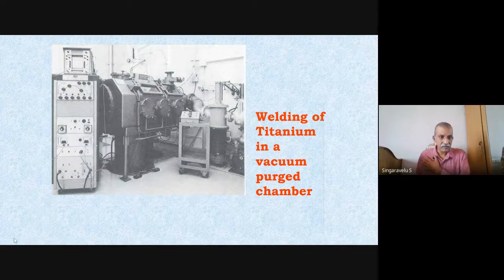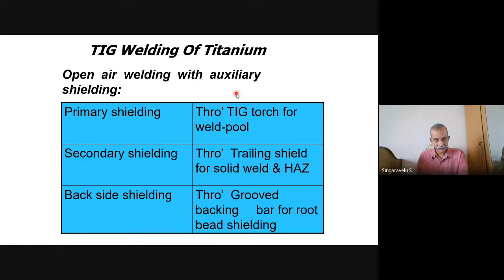Okay. And coming to our shielding, I said, in case of open air, primary shielding is through the torch, which has been taken care of. The secondary shielding is the trailing shield. As you know, the already deposited weld metal has to be protected from the atmosphere. That has been taken care of by the trailing shield. This takes care of the solidified metal and the HAZ. Backside shielding is for the root welding, root pass protection, right? That is the grooved backing bar for root bead shielding.